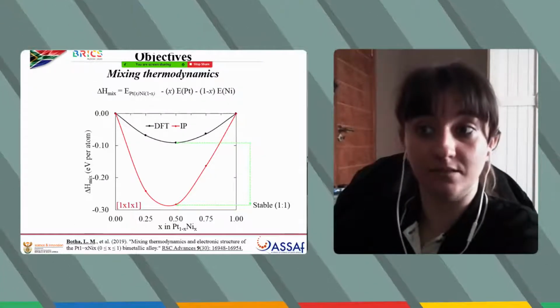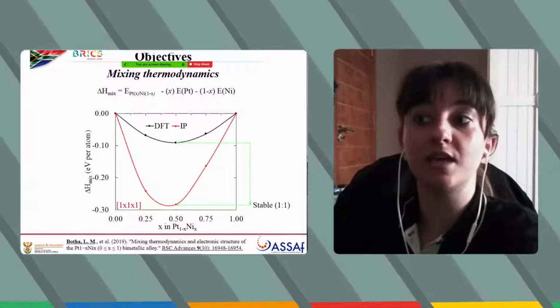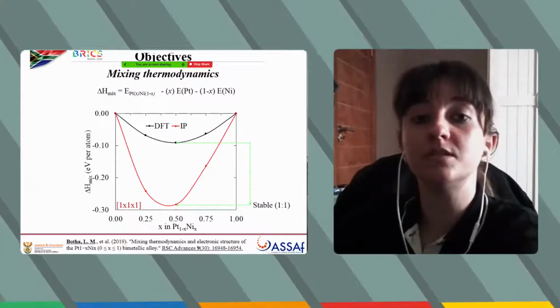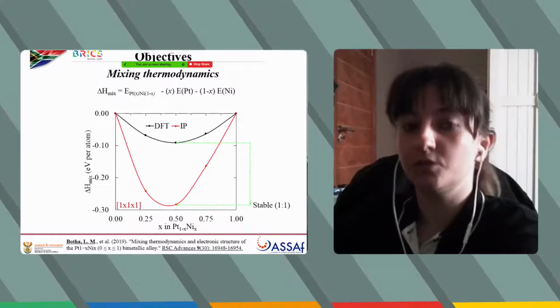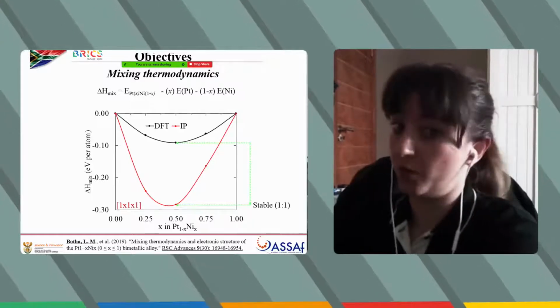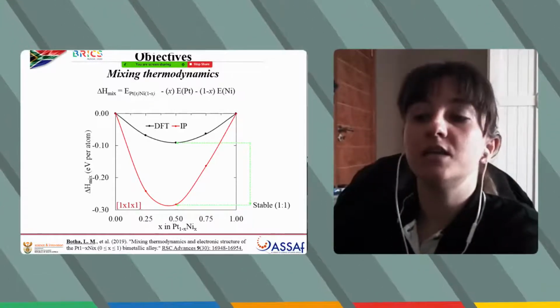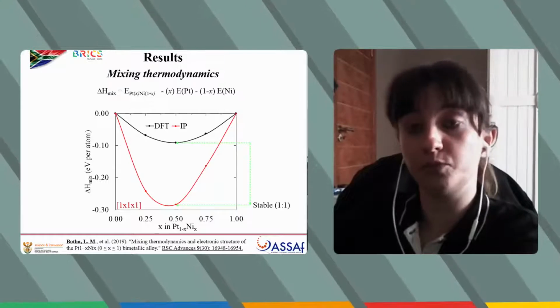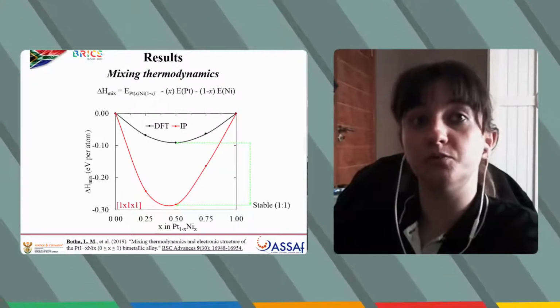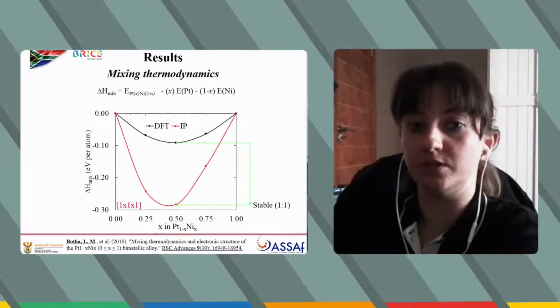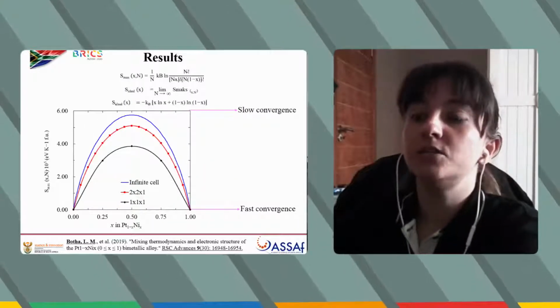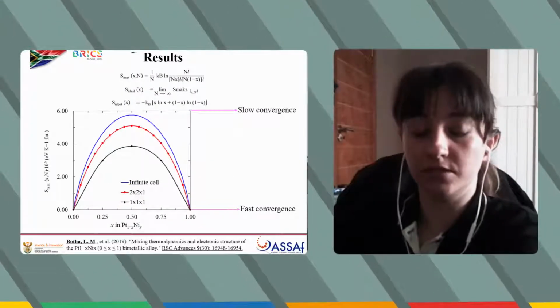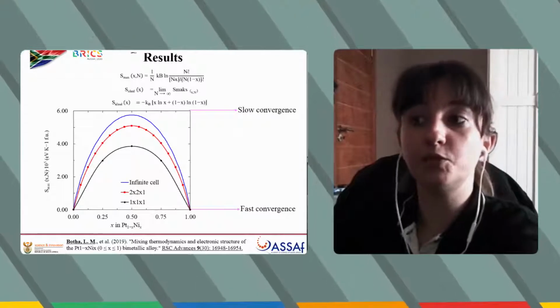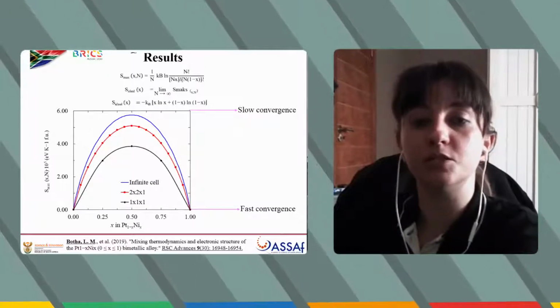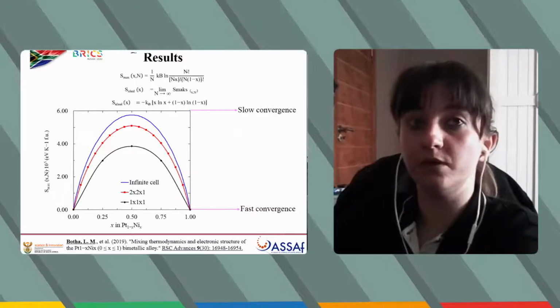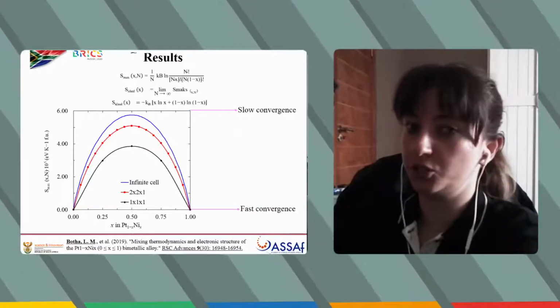Using the small cell, the mixing thermodynamics was calculated to determine the most stable slab to be that of the 1-to-1 ratio, or 50%, as seen by the red line for the interatomic potentials, which was also confirmed with DFT. To determine the optimal size of the cell, the maximum entropy of each of the cell sizes is compared with the entropy of an infinite cell, as shown.